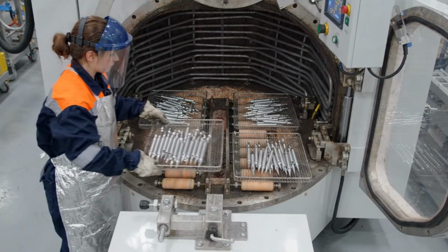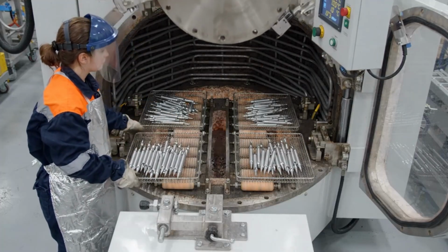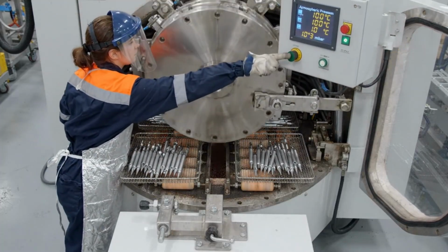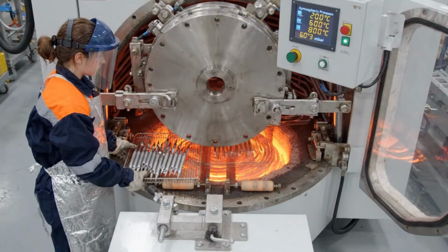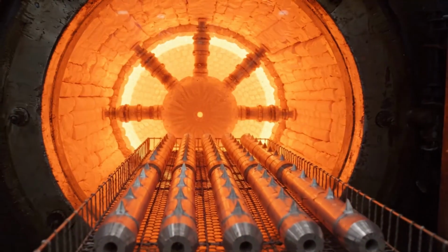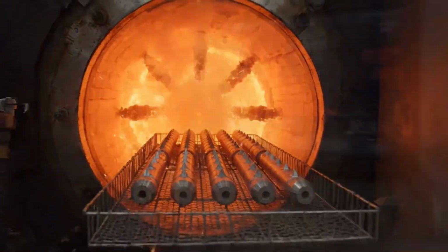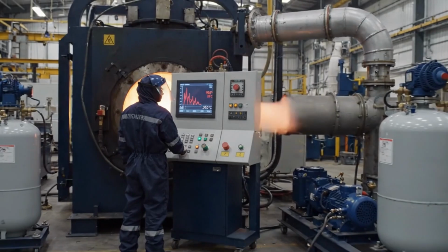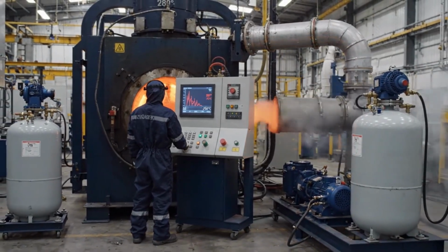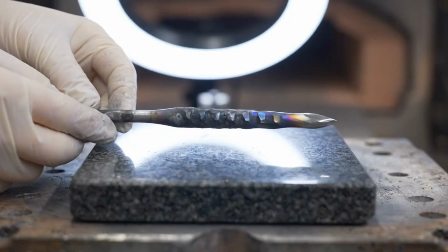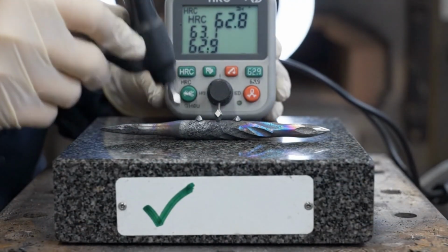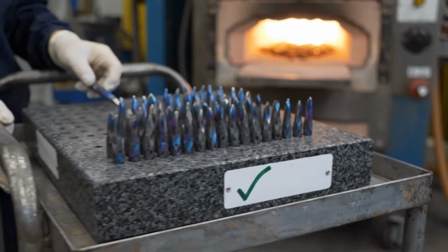At 980 degrees Celsius in a near-perfect vacuum, the chromium and carbon atoms in the D3 steel dissolve completely into a single phase. The nitrogen quench transforms the face-centered cubic austenite into body-centered tetragonal martensite in under 2 seconds. At 63 on the Rockwell C scale, the needle's surface is harder than a file.